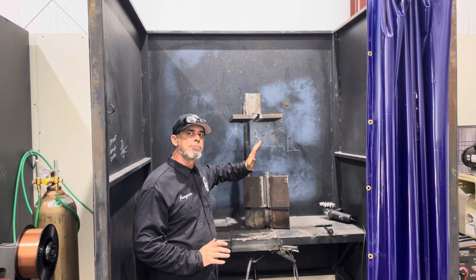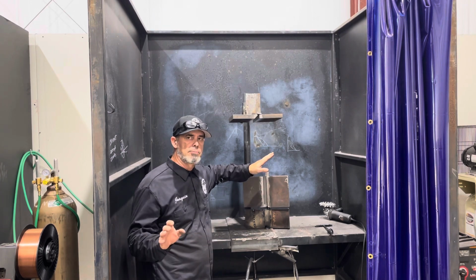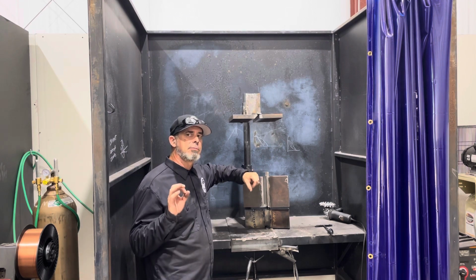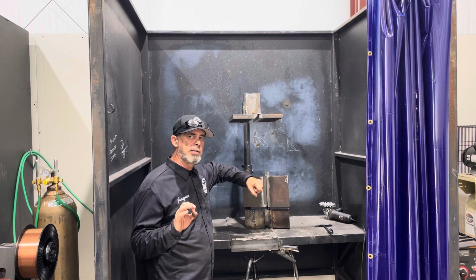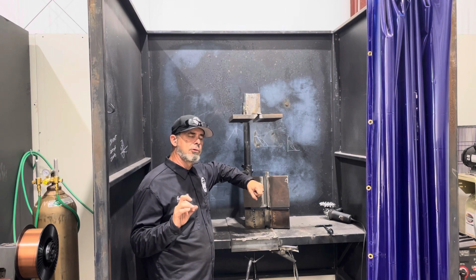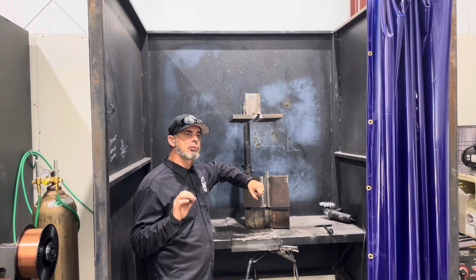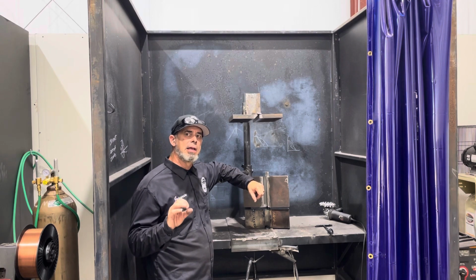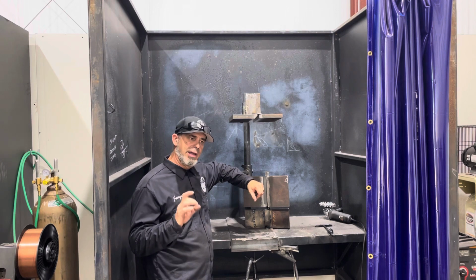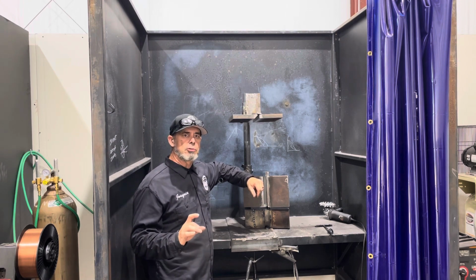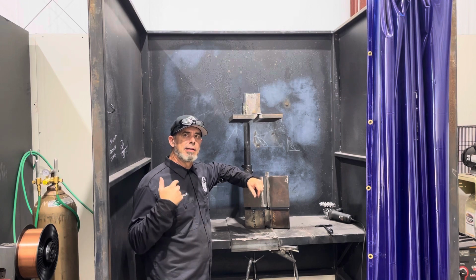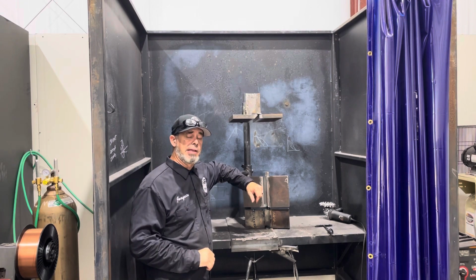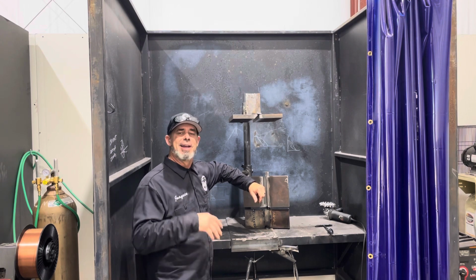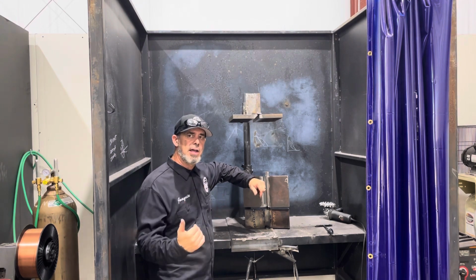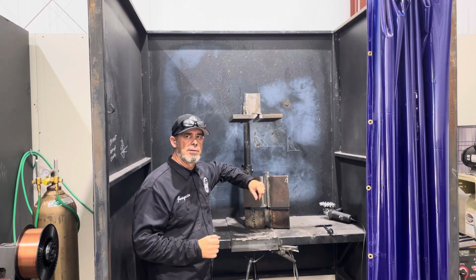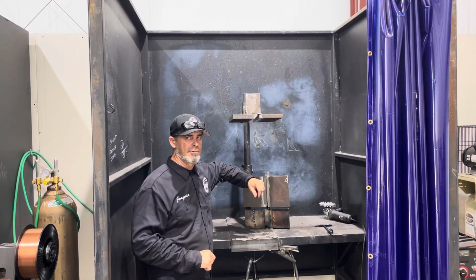Something that you have to be mindful of when you prep up your plates. There's enough videos out there on prepping up your plates, I don't need to go over that. But something that's unique about this, and what I did when I prepped these plates up, was that I used a brand new grinding wheel and a new flapper disc. I made sure that all my surfaces were clean, and clean with the new wheels. Why I did that was because if those wheels were used on subpar material before, and if it somehow impregnated the surface of my material, I don't want that to be a condition that affects the testing of these specimens once I cut them from the coupons.